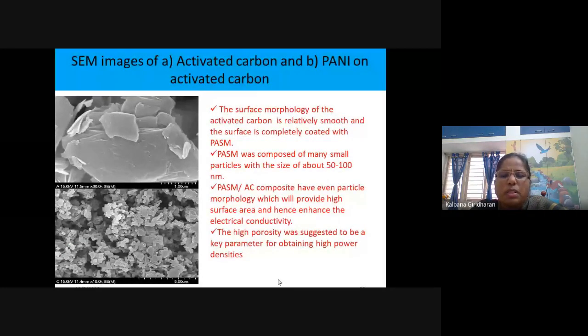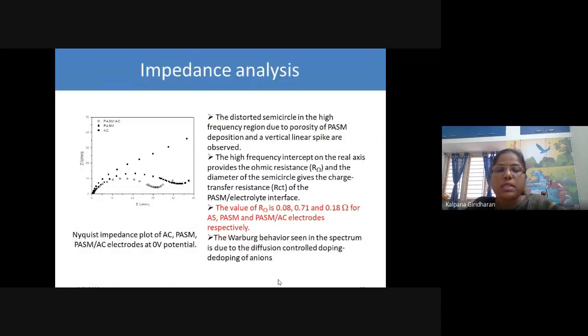This consists of small particles with a nano size of 50 to 100 nanometers, and this composite, polyaniline with activated carbon composite, has a morphology of high surface area which enhances electrical conductivity. The high porosity was suggested to be a key parameter for obtaining high power densities.